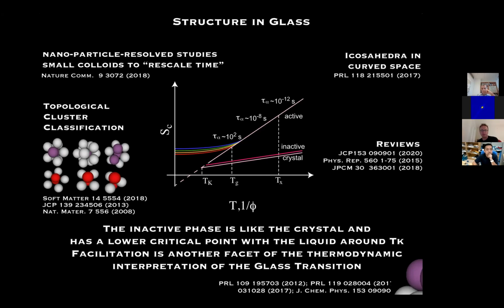I mean, if the particles are a certain shape and they tessellate, then they'll just crystallize, and you can morph between two crystallizing shapes, and in between they don't crystallize and are a good glass former, and then there's a local structure that relates to that. In the system she looked at, it was tetrahedra going to octahedra, and you can morph between the two, and then in between they make dimers which seem not to want to crystallize, if I remember. So yeah, it's possible.